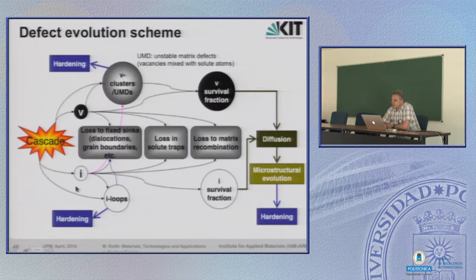Then all the rest of interstitials and vacancies which haven't recombined, they build a survival fraction. They diffuse through the lattice, and through this enhanced diffusion going on in the lattice, they change the microstructural evolution. And if the microstructural evolution is changed, this also results in hardening. So, in one word, the final effect of all these remainders of the cascade is hardening of the material.